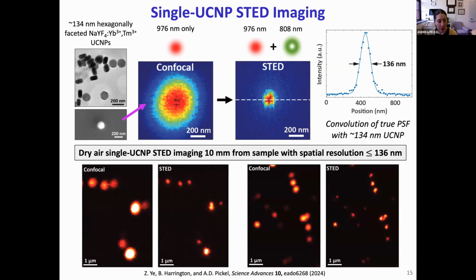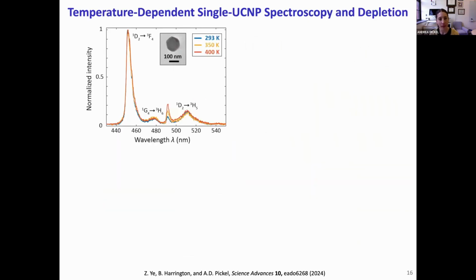We can also look at larger scans containing both single UCNPs and small aggregates. And if we compare the same scans without and then with the STED laser, we see that the spots appear smaller. And we can also see spots that were previously blurred together start to separate into more distinct isolated spots. So we were happy to demonstrate single UCNP STED imaging, but again, if we want to do ratiometric STED nanothermometry, then we need to do spectroscopy.